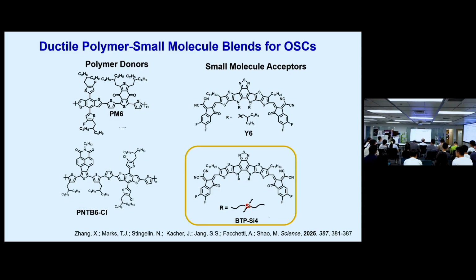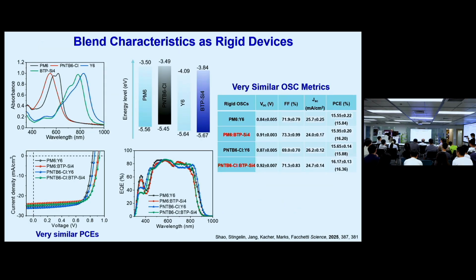Well, think of simple chemistry. Carbon tetrachloride you expose to air, it just sits there. Silicon tetrachloride fumes, and it's the ability of the size, the orbitals that are involved. And silicons also have interesting properties. They're very hydrophobic. Just putting that silicon there, and they can lower the glass transition temperature of lots of polymers. So if we combine all of that, and this is what we've done here, we've made a whole series, and the chain just has one silicon in it.